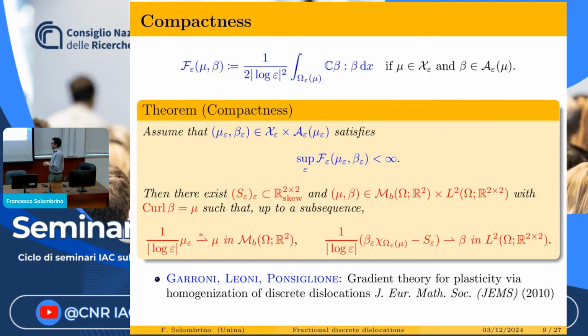So this is not only mathematical abstraction, this is something that has to happen. If you want a minimal model of this sort, which may be wrong from a lot of points of view, but is what people are currently using to understand the phenomenon, you have to accept that your elastic strain is an L2 function and you like it, while your plastic deformation is way uglier from the point of view of the structure, because it may have some concentration, so it may be a surface measure, or it can possibly develop other kinds of singularities. So you cannot describe it by functions. You really need measures.